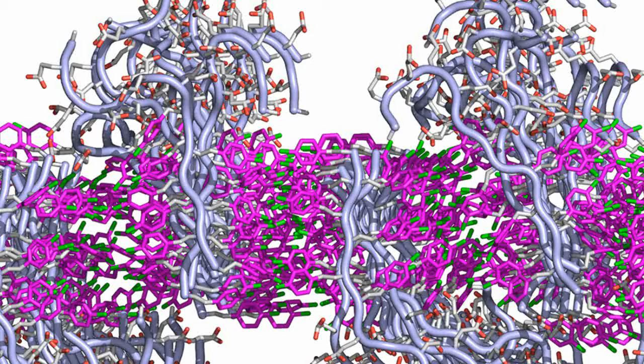To test whether their synthetic membranes had the signaling ability of cell membranes, the researchers added a touch of sodium chloride salt. Salt is involved in the last step in many signaling sequences and causes real cell membranes to thicken up. The peptoids did too. The more salt the researchers added, the thicker the nanomembranes became, reaching about 125% of their original thickness in the range of salt concentrations they tested.